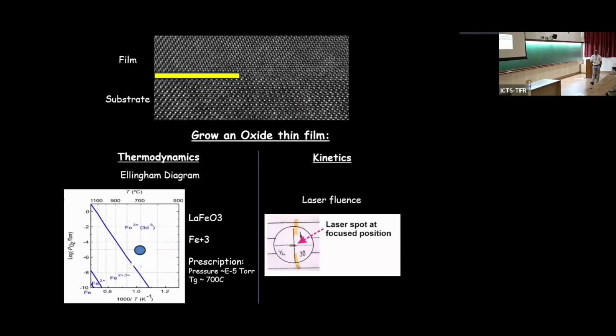This is a TEM image of our sample. And while growing the sample, you can use thermodynamics, where you can use what is known as the Ellingham diagram. For example, if you want to grow iron in the 3+ state, then you should try to come here, because if you grow here or here, there is a possibility. So this is 1 over temperature, and this is the oxygen partial pressure on a logarithmic scale. So if you grow here, there is a possibility that you can get the iron in the 3+ state. Of course, there is some deviation there.